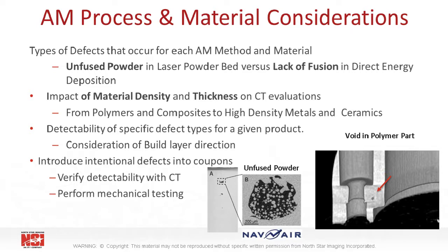Some of the process considerations that can impact CT are the types of defects that occur for a given AM method and material. For example, unfused powder in the laser powder bed process compared to lack of fusion type defects using the direct energy deposition process. The location and the orientation of defects are also factors to consider, and the material density and thickness of a part can also have an impact on image quality. By introducing known defects into test coupons, we can verify the detectability with CT and then perform mechanical testing on the coupons. This NavAir provided image of an unfused powder defect is a great example of this. These are all really good reasons to make use of known defect standards for qualifying both the AM and CT processes.